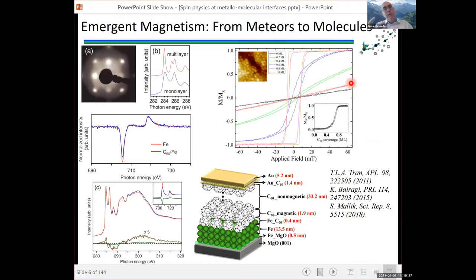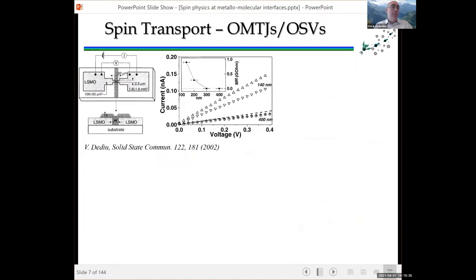People then also wanted to start to grow devices with molecules. The first successful measurement of magnetoresistance in a spintronic device with molecules was the one from V. Dediu, where they have LSMO, a manganite with high spin polarization, theoretically half metallic, or at least high spin polarization, but not very high Curie temperature. And Alq3, a molecule that was typically used for measurements of electroluminescence in between the electrodes.